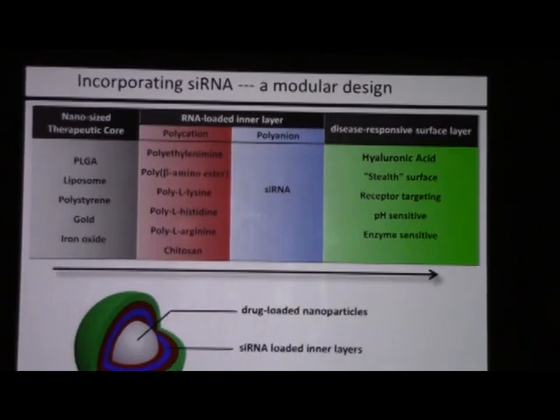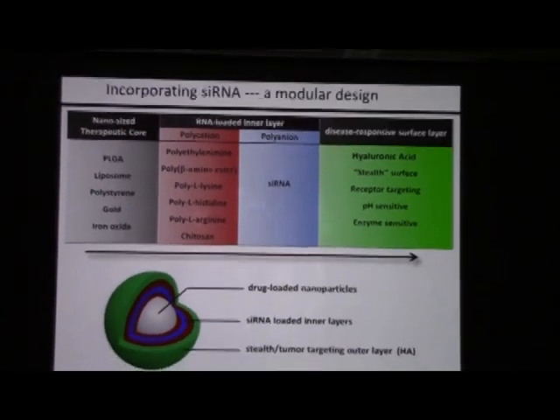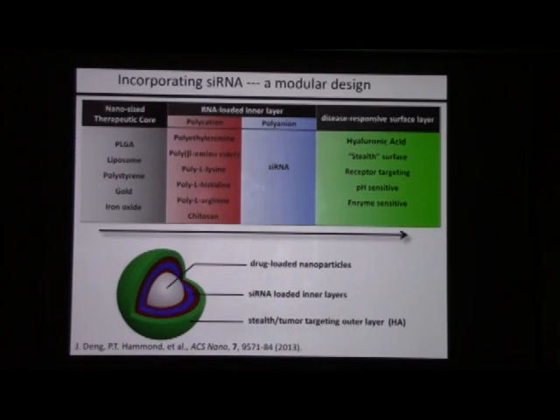All right, so we can generate this outer layer to get the nanoparticle where it needs to go. And now let's talk very briefly about incorporating siRNA into this middle layer. We represent it as this blue color here. We looked at a bunch of positively charged polymers that could layer with the siRNA. And after optimizing, we found one that works really well, that is a simple polypeptide.